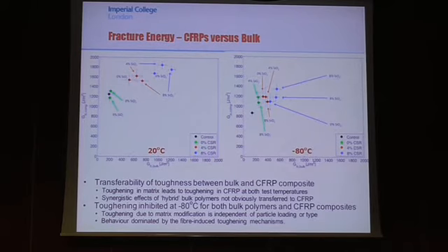So the increase in toughness in the matrices is approximately the same as the error bars within the composite. So the synergistic effects of the hybrid bulk polymers is not transferred to the CFRP at both test temperatures. We see here that as we go on the bulk, we go 0 for 8, whereas it goes 0 for 4, and then adding 8 silica actually makes the response of the fracture toughness of the composite worse. So the behaviour of these carbon fibres is dominated by the fibre-induced toughening mechanisms, but adding in the modified matrix does increase the toughness of the composite at both 20 degrees and minus 80 degrees.